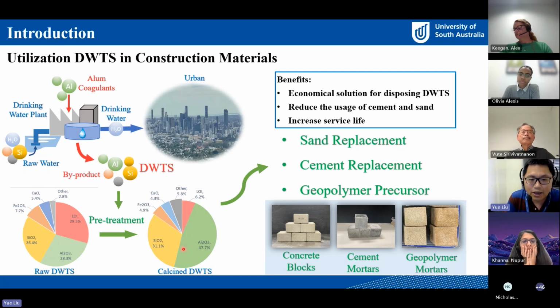For the pozzolanic reaction, the aluminum and silica content in sludge will react with the calcium hydroxide produced from the cement hydration to produce some secondary C-S-H gel. Some products we have already developed, like concrete blocks, cement sludge mortar, and geopolymer mortars.